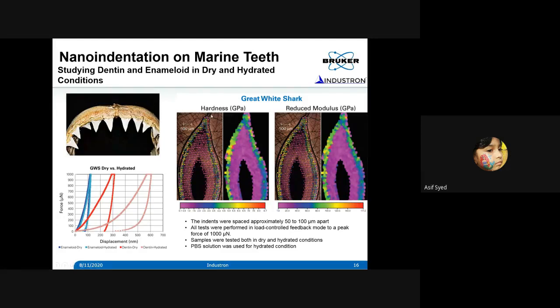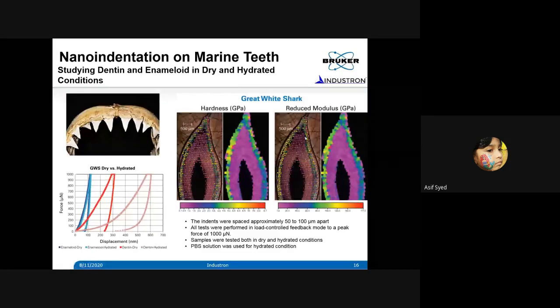On the left side, what I'm showing is the hardness measurement and where the indents have been done. You can also see the extrapolated map, which gives you an idea of how the hardness on the surface is distributed. It's very hard at the periphery, and as you go into the interior, it becomes softer and softer. And on the right side, I'm showing the reduced modulus again as a map.